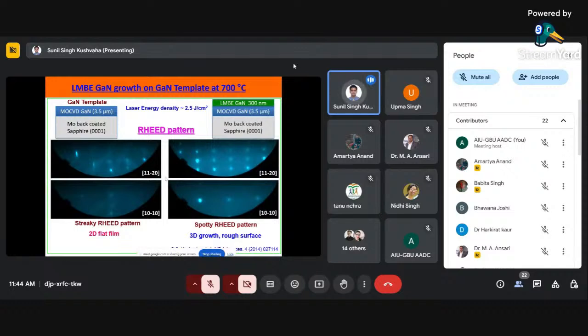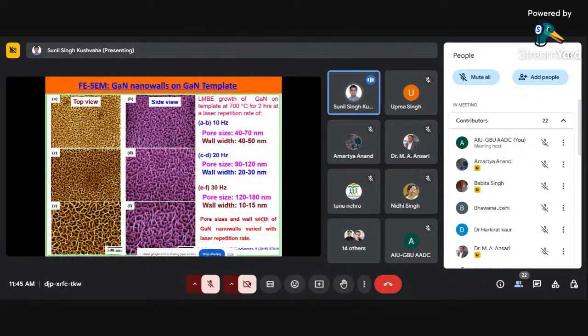Of course, every system comes with in situ characterization techniques. One of the in situ characterization techniques is RHEED, that is reflection high energy electron diffraction. Even during the growth, we can see, for example, when we have the gallium nitride template, we can clearly see the formation of only a streaky pattern. But when we are growing the film, we see a spotty pattern, which clearly shows that our gallium nitride growth is happening. So this is one of the techniques by which you can know even before taking out the sample.